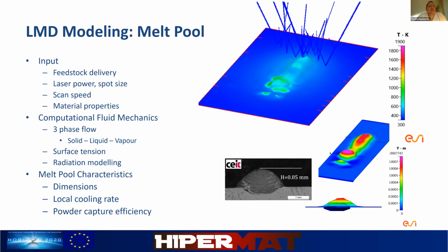Radiation modeling is quite important for LMD. There are other additive processes where radiation can be simplified to a very simple, analytical formulation. But in LMD, you have to resolve radiation in a more elaborate manner because the nozzles used are usually coaxial, meaning the laser is delivered through a central hole of the nozzle and particles flow around the laser. So you have actually scattering of laser power by the particles. The amount of energy reaching the substrate or absorbed by the powder before it actually reaches the substrate are things which are calculated in the model and are extremely important to capture the melt pool dimensions correctly.